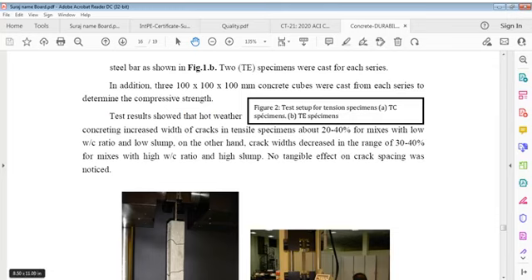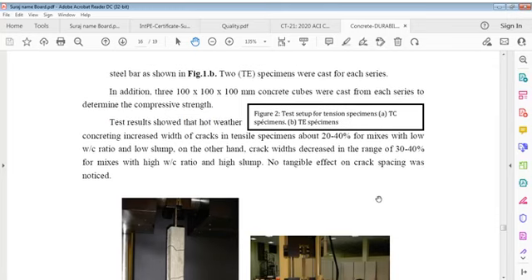Test results showed that hot weather concreting increased width of cracks in tensile specimen about 20 to 40% for mixes with low water cement ratio and low slump. On the other hand, crack widths decreased in range of 30 to 40% for mixes with high water cement ratio and high slump. No tangible effect on crack spacing was noticed.